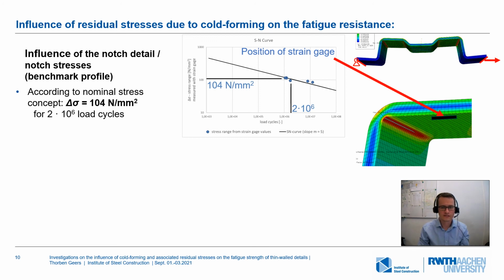The influence of the notch can of course be shown with the help of FE models. This is shown here as an example for a single test series. For the stress determination at the location of the strain gauge, the SN curve shown here results. With 2 million load cycles, this gives an average fatigue strength of 104 Newton per square millimeter with a slope of about 5.